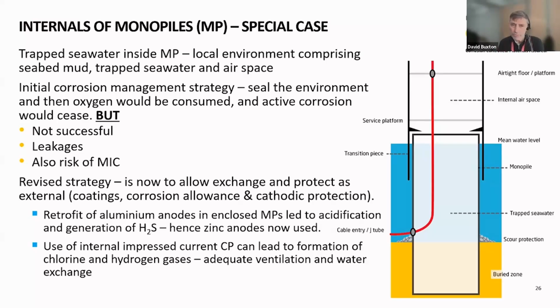The initial corrosion management strategy was to seal this whole environment, with the idea that oxygen levels would generally reduce because they'd be consumed by a small amount of corrosion, and then the corrosion rates would reduce to minimal levels. However, in many cases, this wasn't successful.